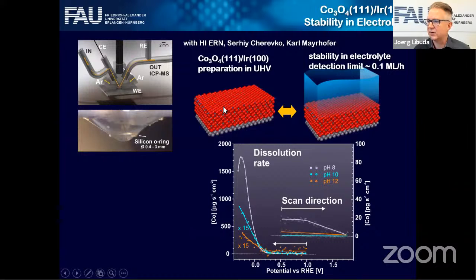We look, for instance, at cobalt oxide surfaces, and you can detect dissolution rates that are in the order of 10% of a monolayer per hour. So really surface science sensitivity. If something changes at the surface science level, you can see that. Unbelievable sensitivity.